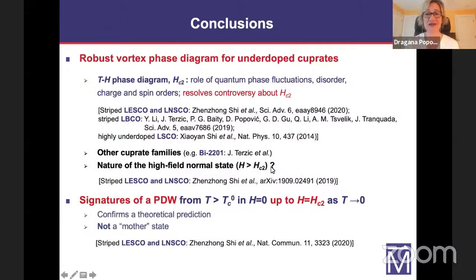We have data, obviously, for the Hall effect at lower fields, and we show that in these two materials it's again largely dominated by vortex physics. But again, the question is, what is the origin of that? There are several possibilities, but in standard models the Hall coefficient can vanish only accidentally, if you have cancellation for a given temperature and field. What's peculiar is that this happens over a wide range of fields and temperatures. So we do not know what the origin of this is. It is certainly a new and very intriguing property of this high field normal state, which should also be probed by other techniques in this high field regime. That's almost a separate talk, and I didn't want to cram too much information here.